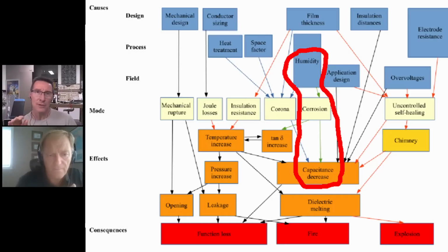So will the moisture eat away at the metal? Will it actually corrode the metal? And what sort of metal are we talking about here for the metallization layers? Well, in some cases there's zinc, but this most likely is not the case. It's usually aluminum. It's probably on the order of 100 angstroms. The dielectric thickness itself, so the film itself, is probably in the order of maybe 1 to 20 microns, something like that. So it's a wonderful part when they work well, and I suppose it worked in a sense.